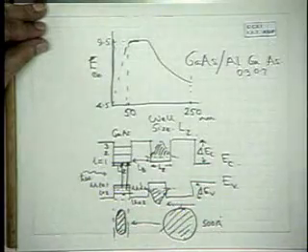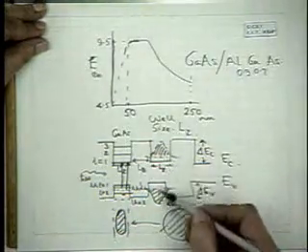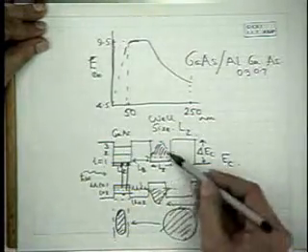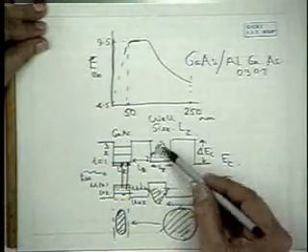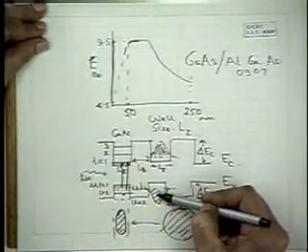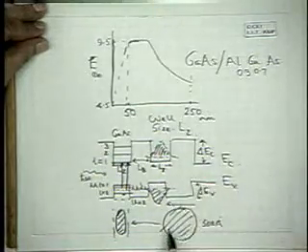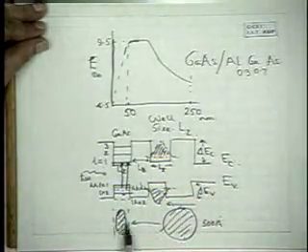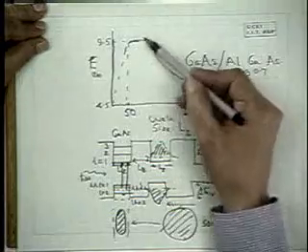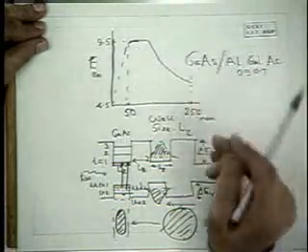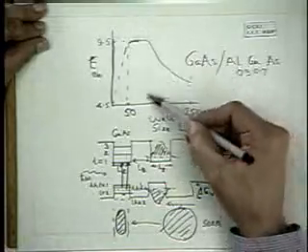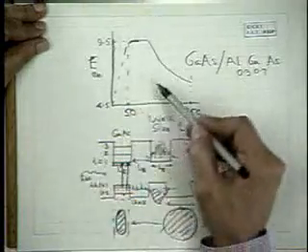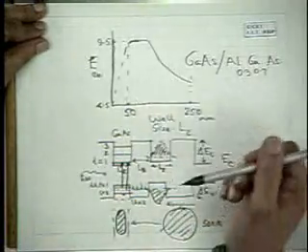So there is going to be strong confinement of the electrons and holes in these quantum wells, and as a result, strong overlap between the electron and hole wave functions in a narrow region. Here, the electron and hole wave functions are spread out over a large region. Here, it's confined. Therefore, that is the physical basis for the increase in the binding energy. If the electron is localized and the hole is also localized, then the exciton binding energy increases much more strongly, and hence these exciton effects are observable at room temperature.